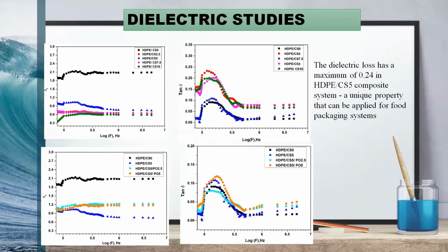Among these factors, knowledge regarding the dielectric properties and thermal stability assume greater importance, as these help in understanding the interaction between the filler and the matrix with which the composites are being prepared. The dielectric constant of a material is related to the permittivity of a material. And we see that on addition of chitosan, the permittivity decreases, the dielectric constant decreases.